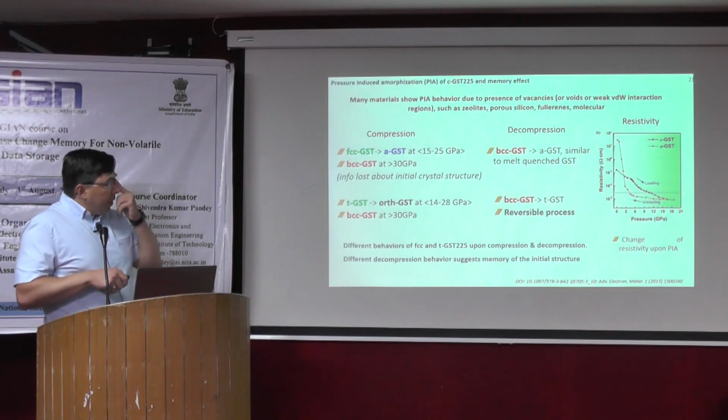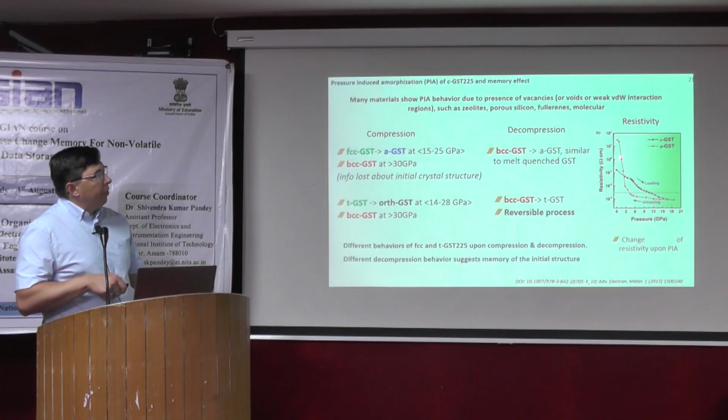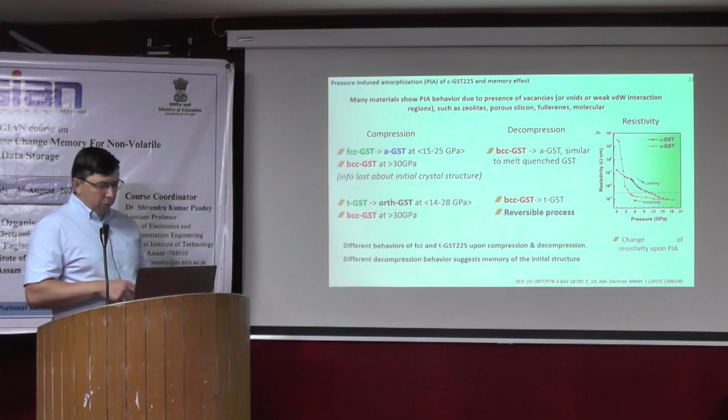Also, there is a change in the properties of the phases. If you compress the FCC GST, the resistivity changes on loading, and then on further compression it goes up to a higher value, showing the formation of the amorphous phase.